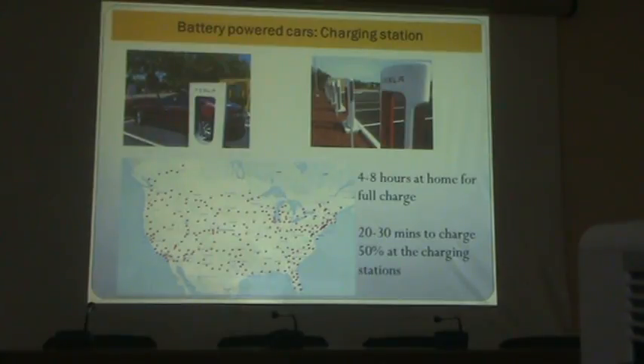And this charging time is very high. If you want to charge it fully, it takes around 4 to 8 hours. If you charge it at least 50% so that you can reach your destination, it still takes around 20 to 30 minutes. So the batteries are still very primitive compared to gas, diesel or petrol.